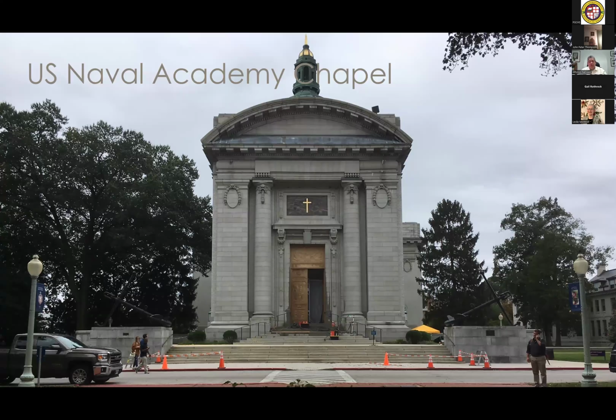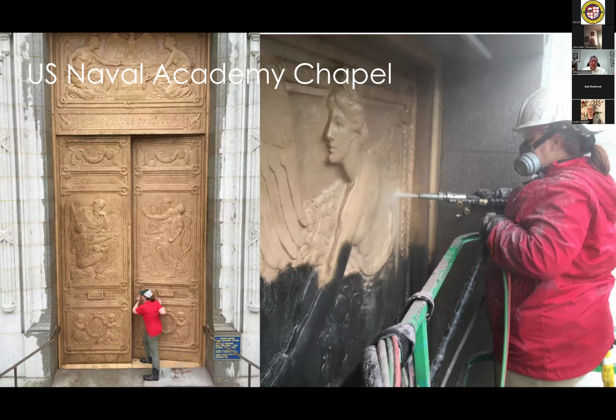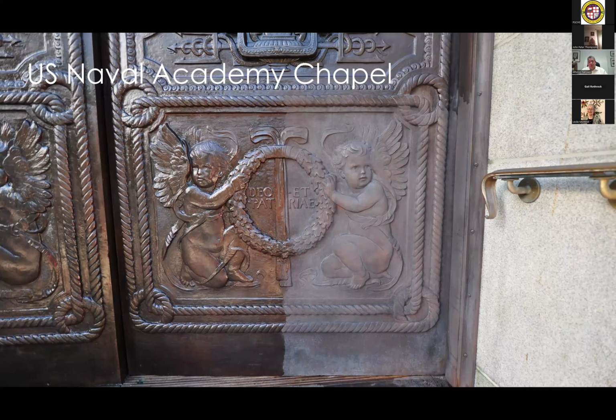We used a similar technique to restore the bronze doors of the U.S. Naval Academy Chapel, this time using a different media. So it's the same system, but now using crushed garnet, excuse me, to remove a painted on coating and lacquer that had been painted on to simulate patina, but was a failed coating. It was falling apart. So we had to remove it 100% and then repatinate the surface and then re-wax the surface. On the right is the patination chemical applied with heat, and on the left is the same thing, heat, but also now wax that will then harden into a very hard, dense wax coating that will protect the bronze.